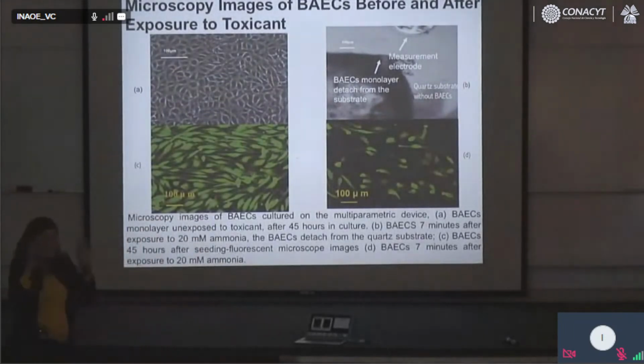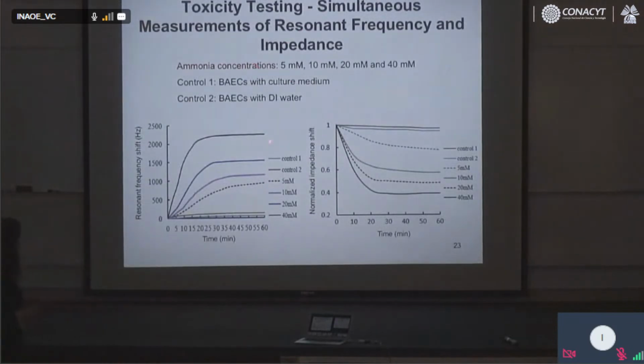In that moment, when you do that 45 hours into the culture and then you introduce ammonia, the cells are dying. And you can see this is before the experiment, very strong monolayer here, and then you introduce ammonia, and then in a very, very short time the cells are dead. And here are our results after you introduce ammonia, and of the resonant frequency. The resonant frequency is growing, is getting up, and the shift. Here is the shift of the resonant frequency. It is getting up because the cells are dead. After you introduce ammonia, they detach. They immediately detach in very short time. You can see here the time of detachment. It's like in minutes. In like 10, 20 minutes, the cells are dead and apoptotic.